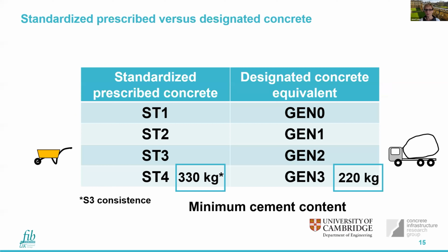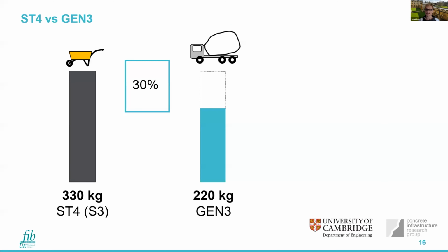And I think what I've picked out are the different values for the different classes, but for example, for ST4, which might be trench fill, we have a minimum cement content or combination of 330 kilograms, whereas for Gen 3 equivalent, we have 220 kilograms. So if we look at this difference, it's significant. If we move from an ST to a Gen 3, there's a 30% reduction in the cement.